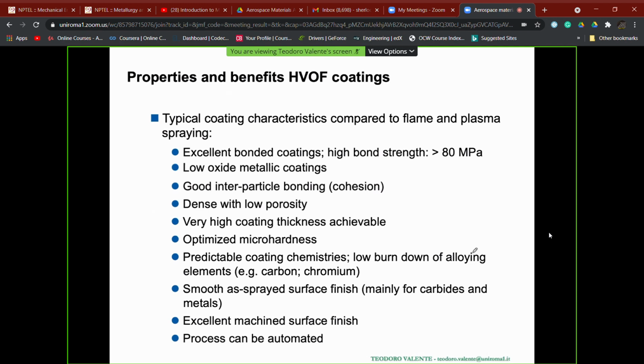All the peculiarities of the HVOF technologies, if we compare to flame, which we have not discussed, another combustion-based process, very poor in terms of technology, but if you compare with plasma, the most important benefit which can be obtained is the very high bonding between coatings and substrate. We can experience this due to the high velocities and the possibility to have the barrel at the exit of the torch, like we have seen in the previous scheme, thus reducing the amount of possible reaction with oxygen, and the possibility to also have a reducing environment inside the flame, in some cases, that depends on the fuel.